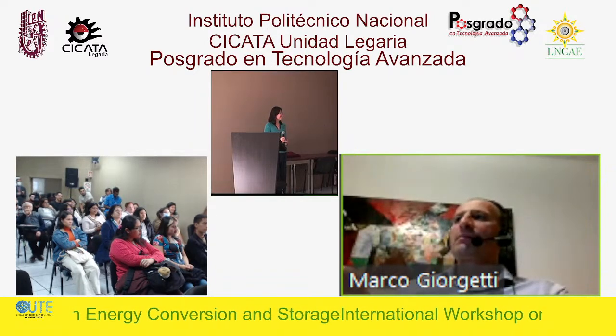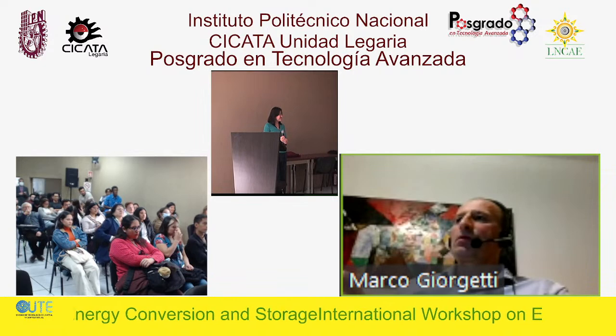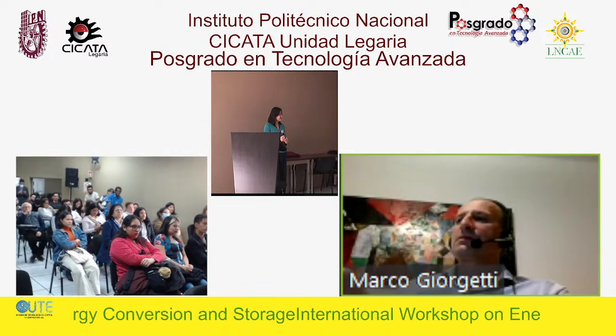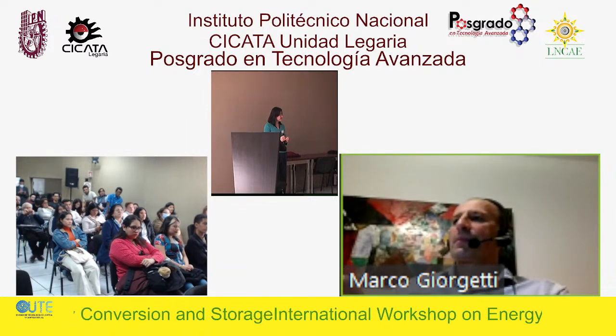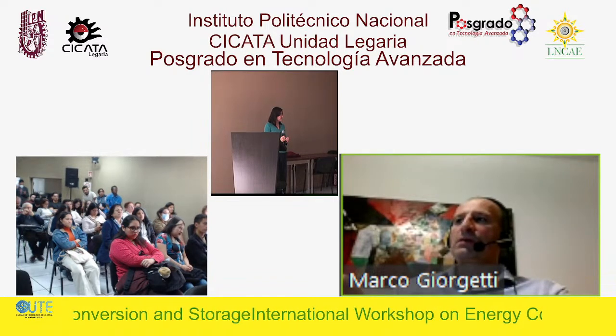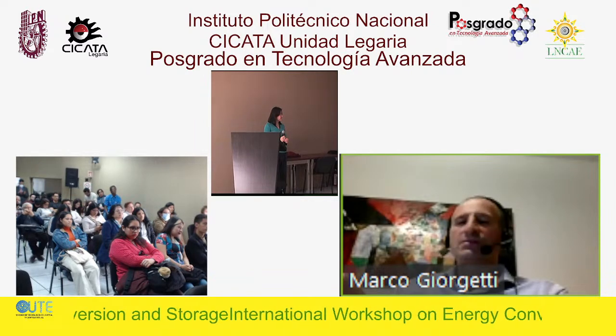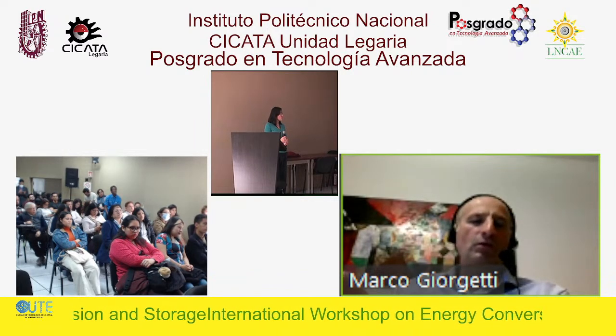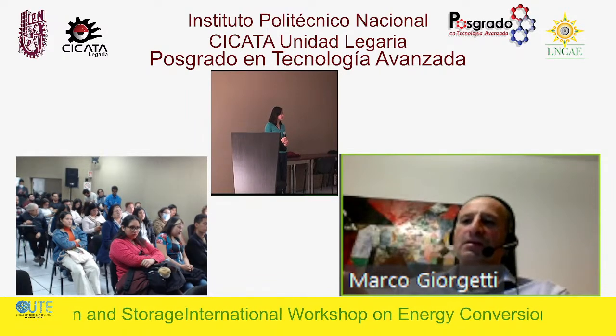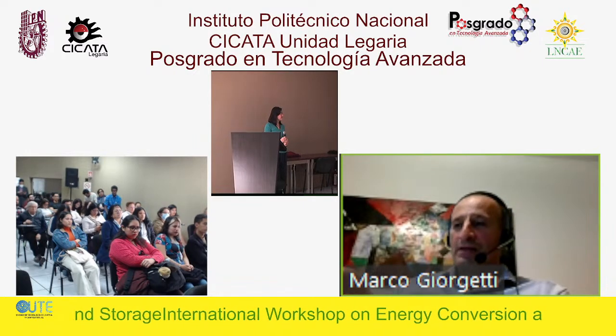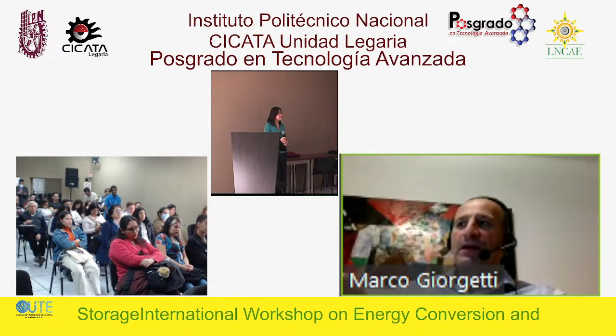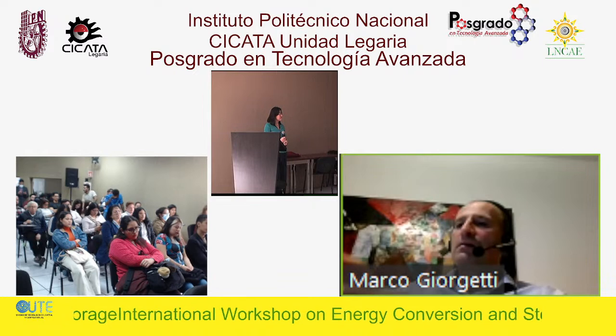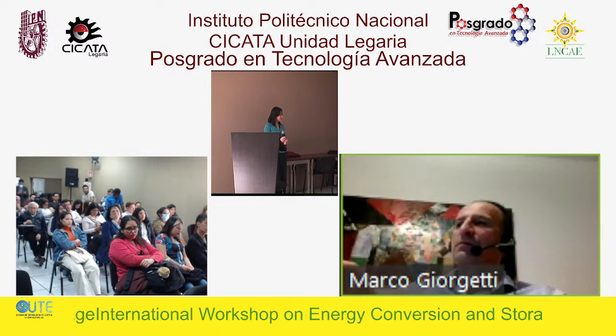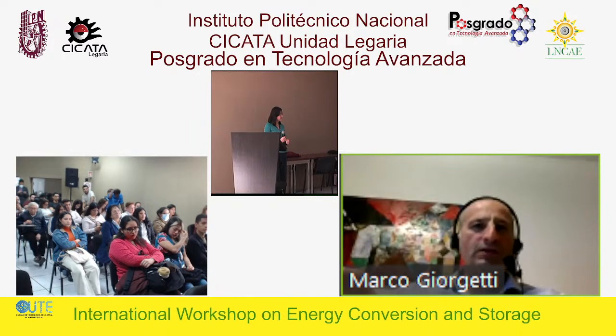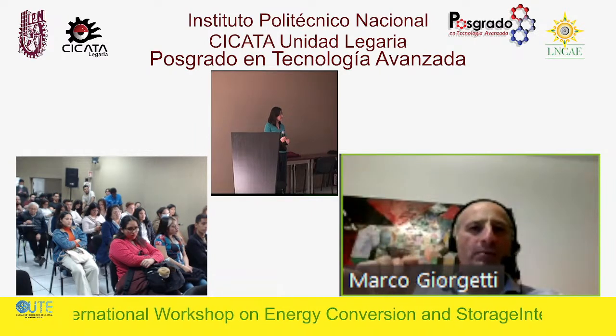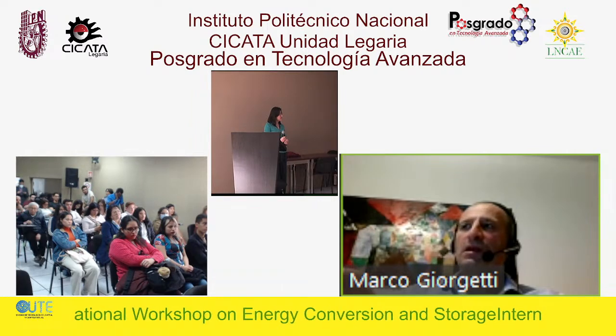Okay, the reason is very well documented by the behavior shown here. The specific capacity reaches 130, 140, and the plateau is very high, 3.5 volts. It's very interesting. Of course, it doesn't reach the plateau of, for instance, lithium iron phosphate, but the specific capacity is extremely high. There is a lot of improvement in capacity with respect to the first paper using this material in batteries, which was about 50 milliampere hour per gram. Here we reach almost 130 milliampere hour per gram.